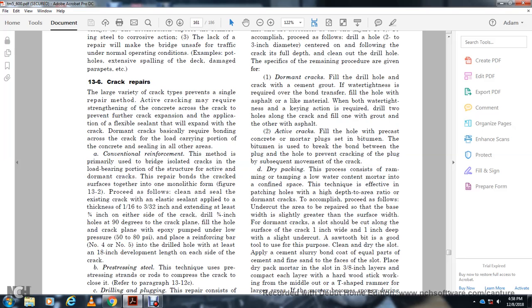Figure 13, top: clean and seal the existing crack with an elastic sealant applied at a thickness of 1/16 to 3/32 of an inch, and at least 1 3/4 of an inch either side of the crack. Drive a drill with a 3/4 inch hole at a 90 degree angle to the crack plane. Fill the hole and crack plane with epoxy pumped under low pressure, 50 to 80 psi. Place reinforcement bar number 4 or 5 into the drill hole with at least 18 inches development length on each side of the crack.